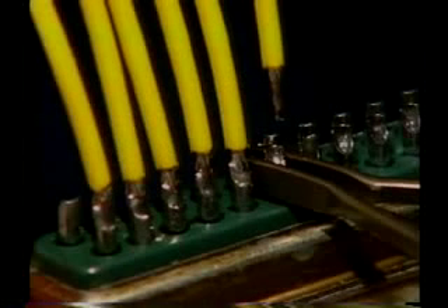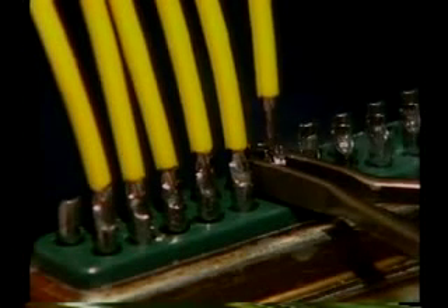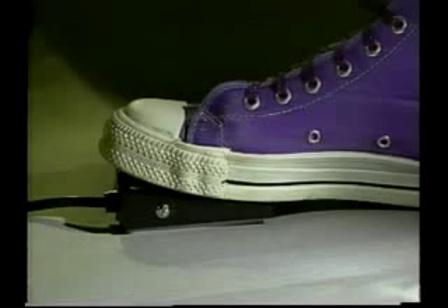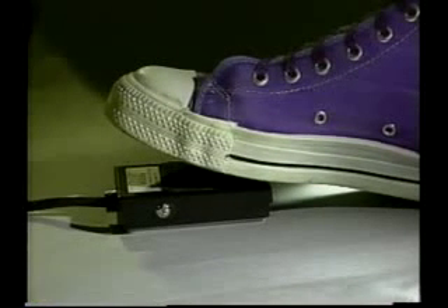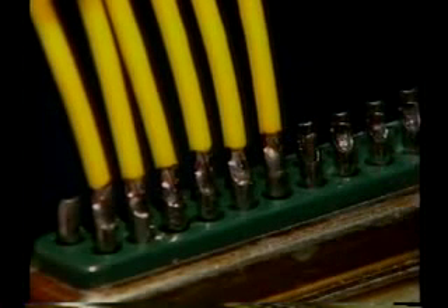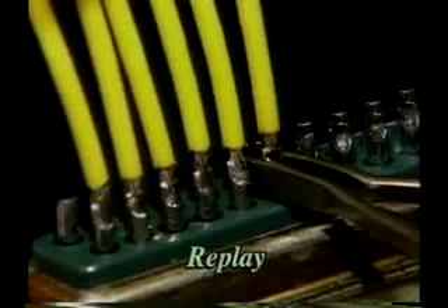When solder flow is observed, the wire can be inserted. Then release the foot switch, and after solder solidification, remove the electrodes. The foot switch should always be released before the electrodes are removed to prevent arcing. Electrical arcing could damage the plating on the terminal.